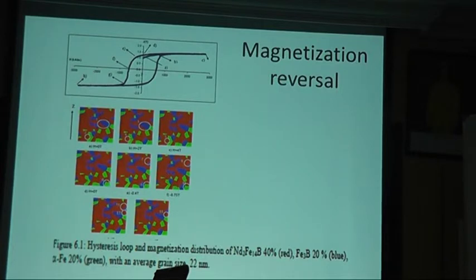But here we can play around with the applied field. We can put even 20 Tesla, but it will take a longer time. So in this case, we can study what happened in here. What's the exchange coupling between these two? The idea is to get the exchange coupling, soft and hard must be neighbor, or the hard grains must be surrounded by the soft grain.